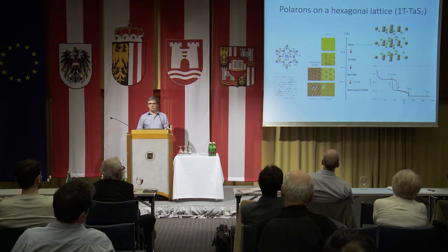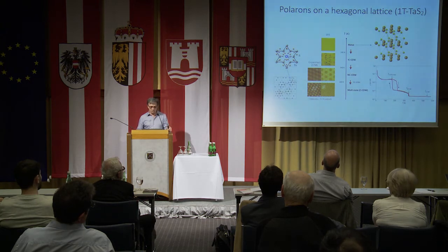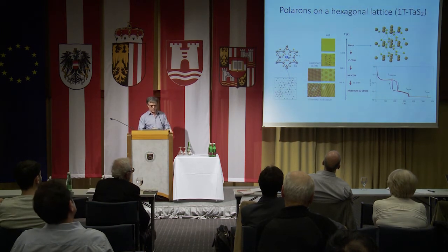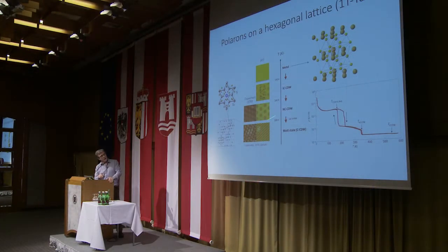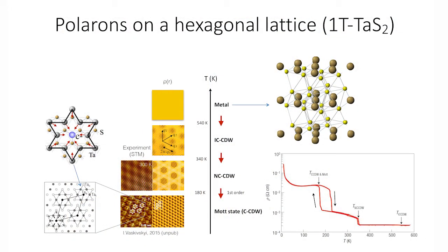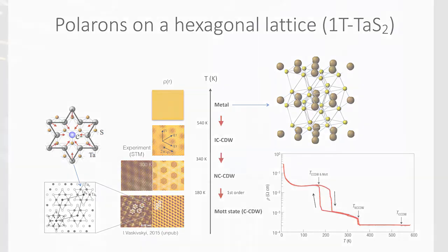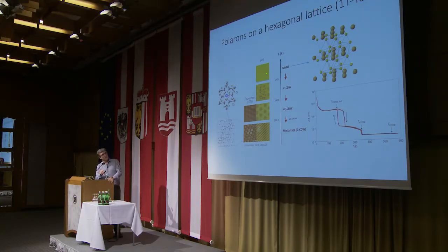Now, there's no time, or it's not really the occasion to go into detail, but let me just tell you a little bit about why this is so. We're using tantalum disulfide in this polytype form. This is a nice layered material which is uniform or metallic at high temperature. As you cool down, essentially, it forms these beautiful waves, charge density waves. As you cool down further, these domain walls disappear, and you get a beautiful hexagonal array of polarons.